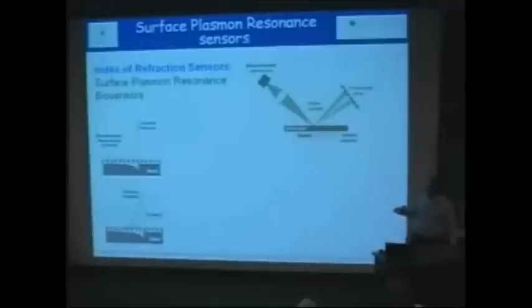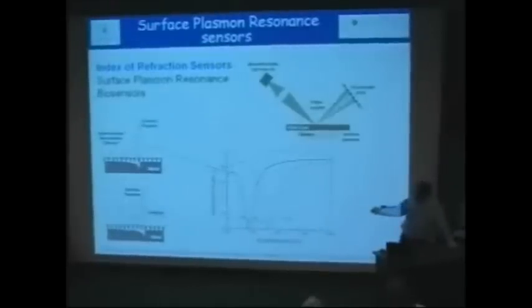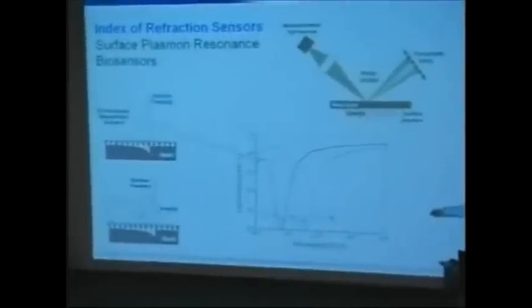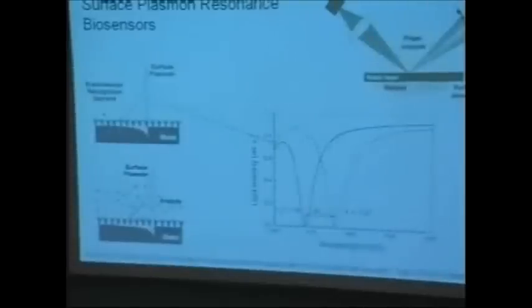So what would happen if you see here on the left, if you would make a measurement, the beginning you would have this thing that is shown on the dark black line, where you had on top of the surface of the metal, this is the metal-water interface, the dielectric is on the bottom, and in the metal dielectric, say this is water, you would have an electric field that penetrates the water. So in this case, we have an electric field that penetrates the water, and because it penetrates the water, if you have antibodies, any change due to an analyte that is captured on the antibodies, as we see here on the bottom, any change would create a local change in the environment, and that local change of the environment is shown as an index of refraction change. So in that case, we would see a shift of the resonance peak.